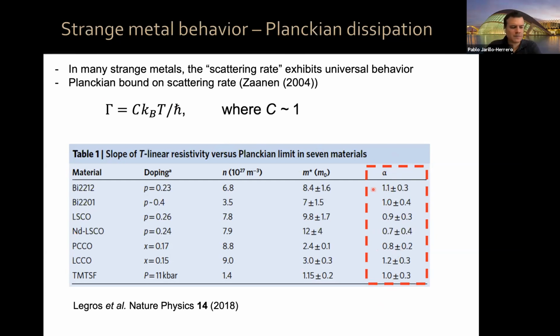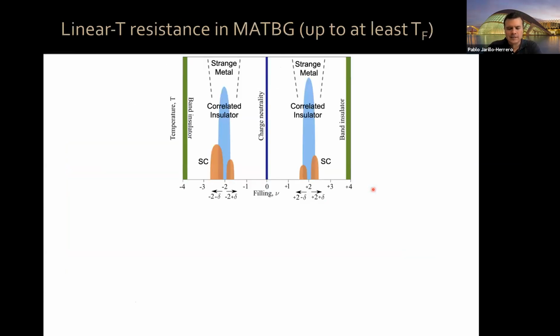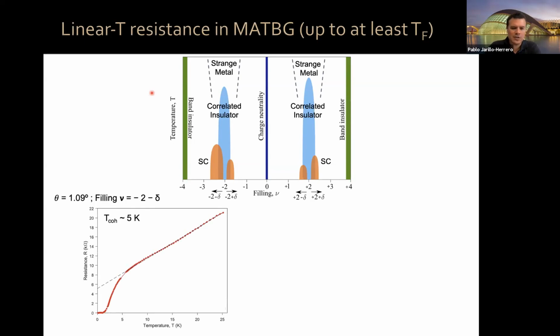So let's look at magic angle graphene. This is again a phase diagram that I showed you before, and if we look in this region near the correlated insulator behaviors for 2 holes per moiré unit cell or for 2 electrons per moiré unit cell, and we measure the resistivity up to higher temperature, you can see this. Here is a 1.09 degree sample at a filling factor of -2 minus delta, so close to optimal doping.